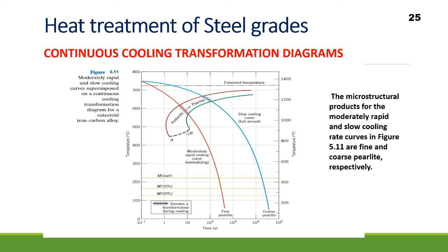if you do continuous cooling of austenite for steel, that is the iron and carbon system, where no other alloying elements are mixed, you will never get bainite. That means bainite will never form. This bainite will not form when an alloy of eutectoid composition is cooled continuously to room temperature. This is because all austenite will have transformed to pearlite by the time the bainite transformation has become possible.